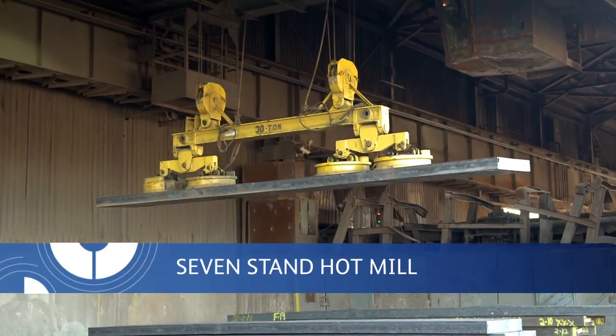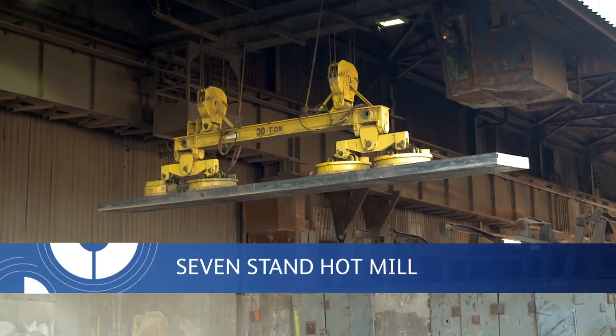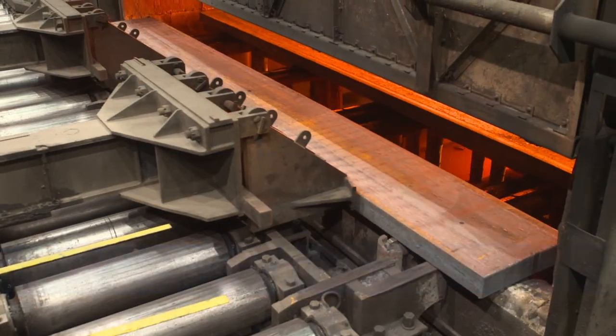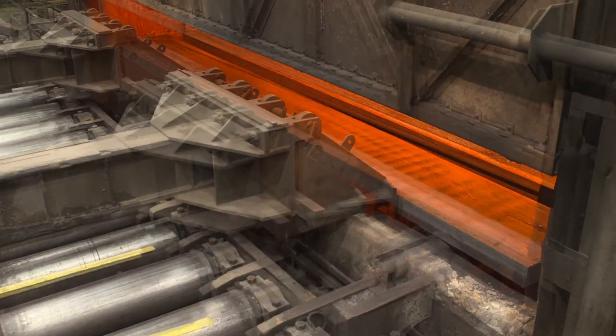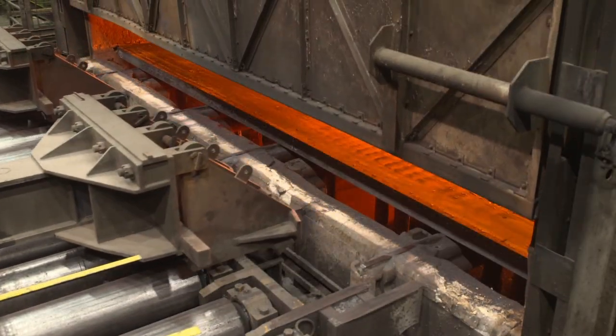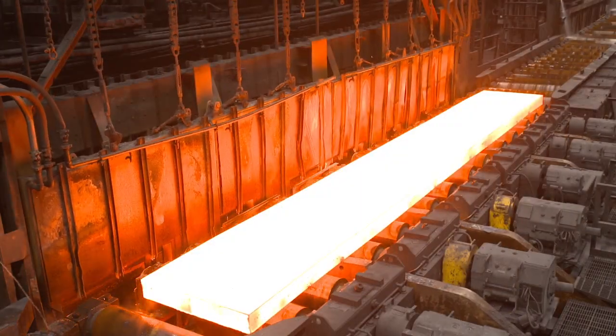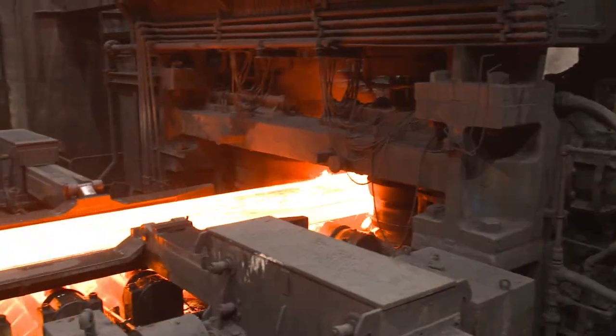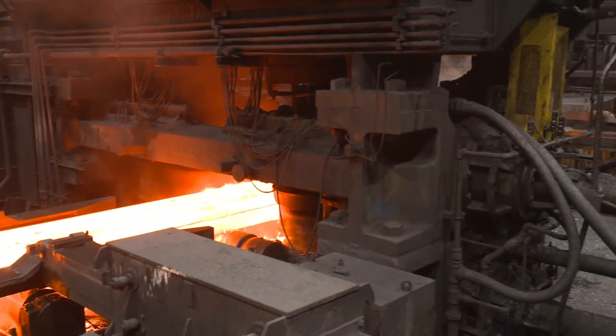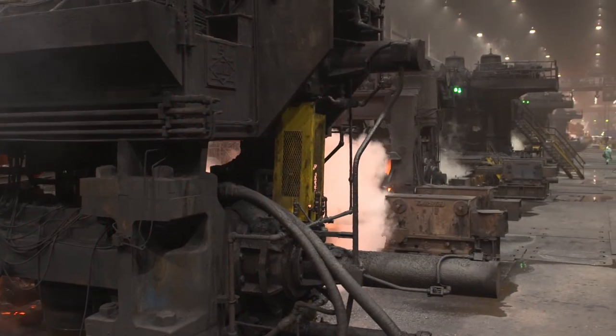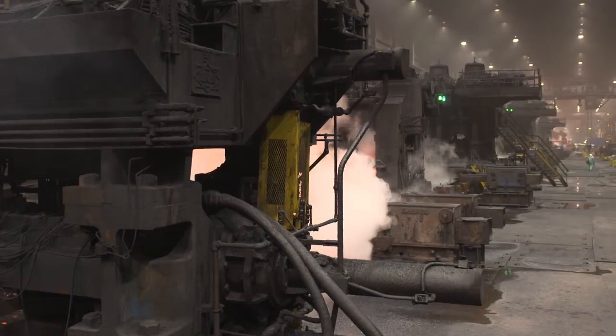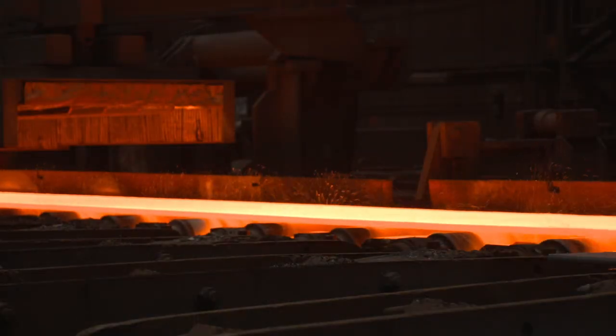The huge slab, which can weigh more than 63,000 pounds, is heated to more than 2,300 degrees Fahrenheit, making it pliable for rolling and hot reduction. As the glowing slab leaves the reheat furnace, it first enters a scale breaker to knock off the scale from the surface before continuing to the 4-stand roughing mill, where the 8-inch thick slab is reduced to 1.5 inches.